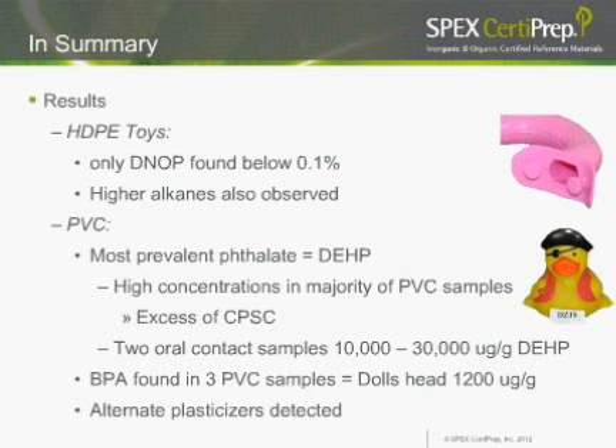For our PVC, the most prevalent phthalate was the DEHP, and there was a high concentration of DEHP in the majority of our PVC toy samples, many of them in excess of the Consumer Product Safety Commission limit. Two of our oral contact samples had between 10,000 and 30,000 micrograms per gram of DEHP.